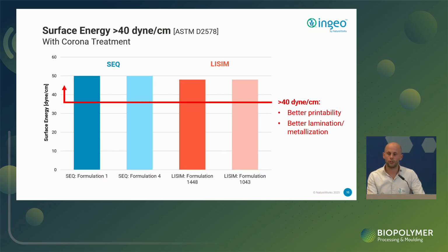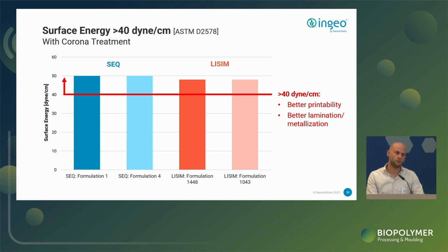Also, the surface energy is important. You should be above 40 dynes per centimeter in order to have a well-printable material, but also if you look at subsequent coating technologies or lamination, you need a certain surface energy in order to have a good performance and adhesion of those coatings.